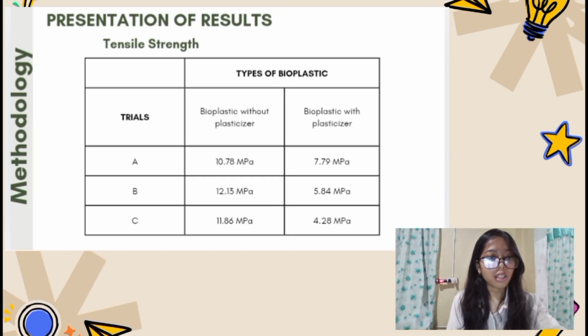And now for our tensile strength. Based on our statistical analysis, the pure agar prototype achieved a significantly higher mean tensile strength of 11.59 megapascals compared to the glycerin formulation of 5.97 megapascals. Our p-value of 0.019 confirms that the addition of glycerin as a plasticizer has a statistically significant impact on the material's mechanical durability, aligning with the findings of Rusley et al.